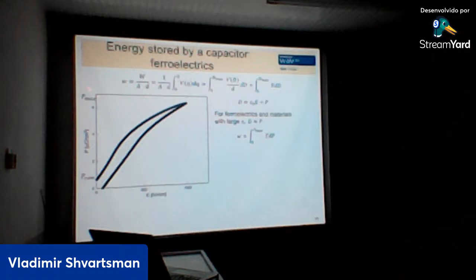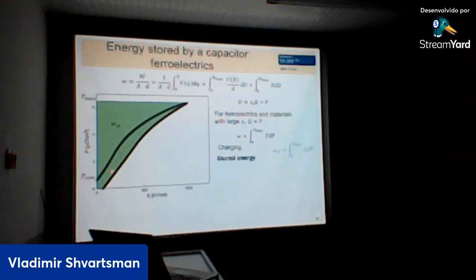Now when we go to the ferroelectric, we speak not about charge but about polarization, which is nothing else than charge divided by the area of the electrodes. And we speak not about voltage, but about electric field. This is an example of our hysteresis loop. Again, to calculate the stored energy, we have to integrate the area between the polarization axis and the charge or discharge curve. The area between the charge curve and the polarization axis is the total stored energy in our ferroelectric capacitor.